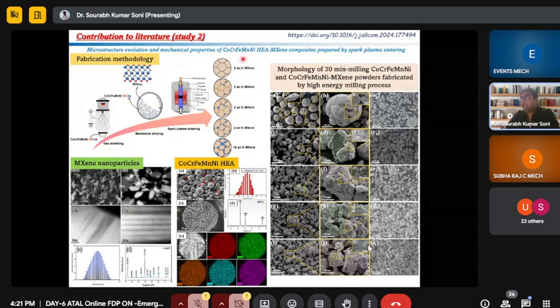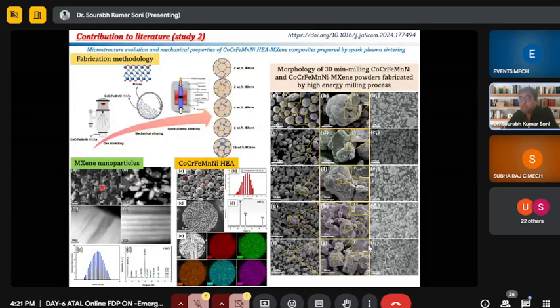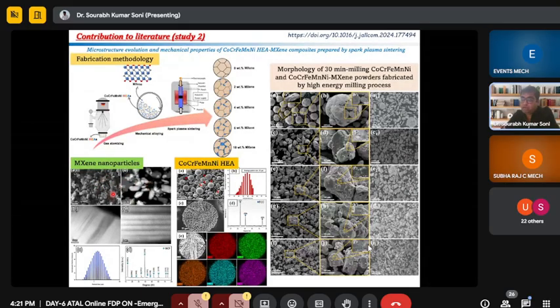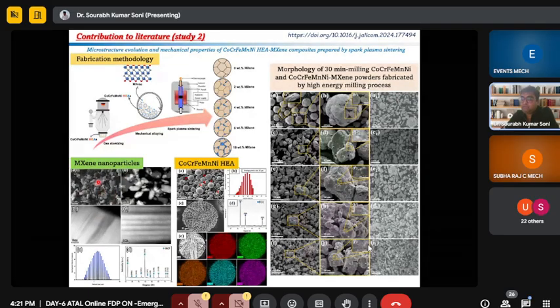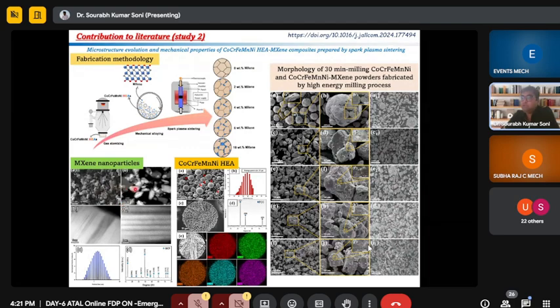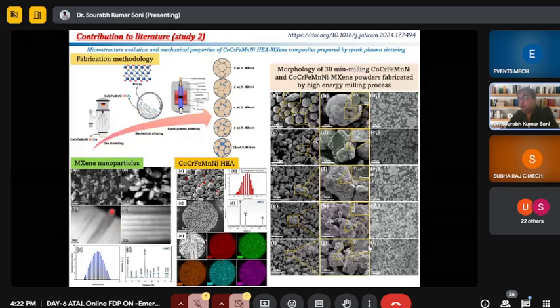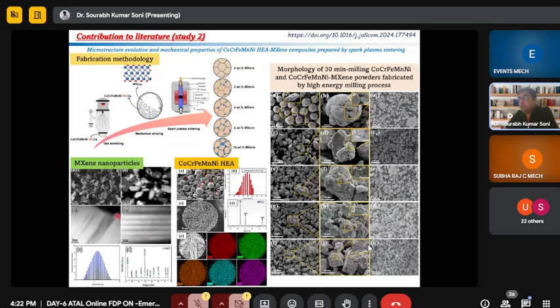In another research, we have fabricated the Cantor HEA with MXene reinforcement particles by SPS. This is the analysis of the MXene nanoparticles using the FESEM. See here, this is the FESEM image. In SEM, you can't observe anything. So you must go for the FESEM for nanoparticles specifically. So this is the FESEM image of the MXene nanoparticle. Then we analyzed by TEM to prove that yes, we have fabricated the MXene nanoparticle. Otherwise, the reviewer will ask whether you have fabricated MXene that belongs to the MXene family or not. So we must follow that procedure.